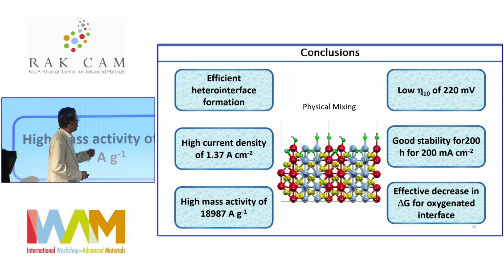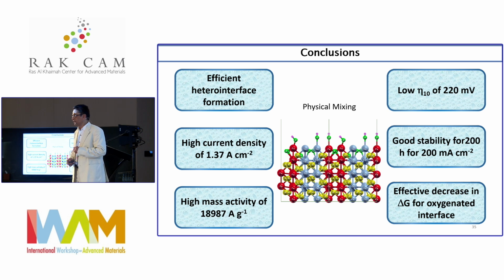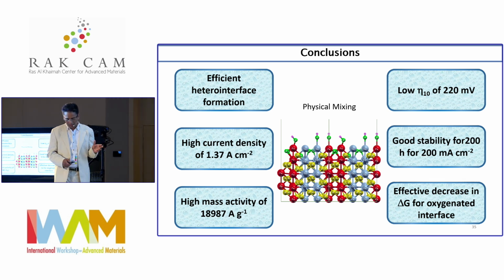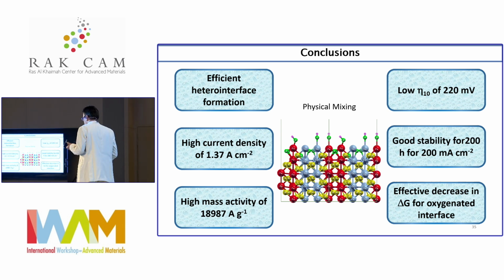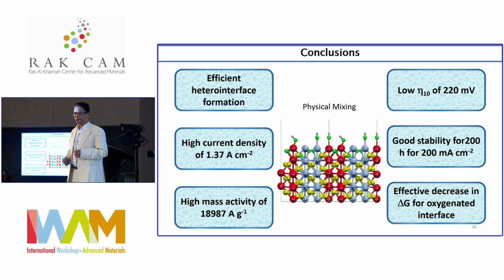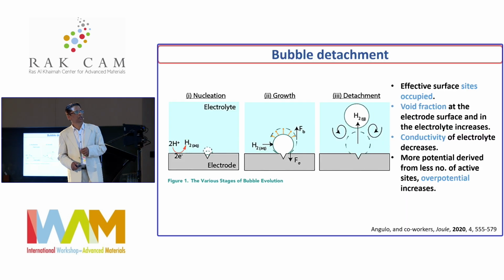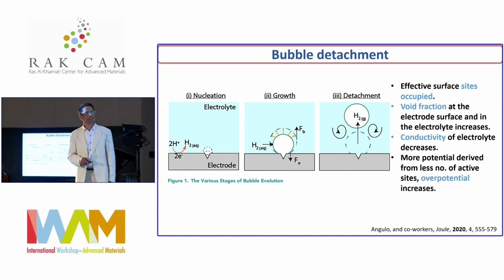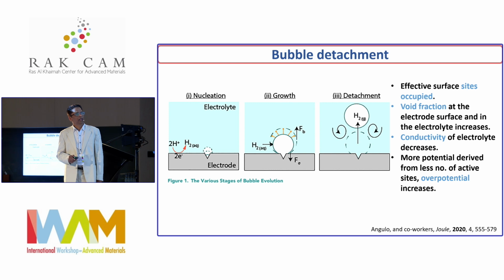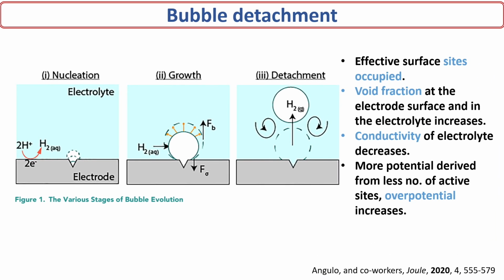And then next I will quickly go through, in a few minutes, the bubble formation in HER and OER, when gas evolution happens. Bubble formation is a big problem that reduces the actual performance of the catalyst. In fact, when a bubble is created, it blocks the sites, the effective surface sites are occupied, and the void fraction at the electrode surface and in the electrolyte increases. It also reduces the conductivity of the electrolyte, and therefore you have to give more potential to drive the same current density. That means the overpotential increases. So there are various approaches.